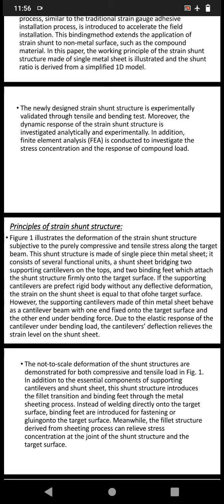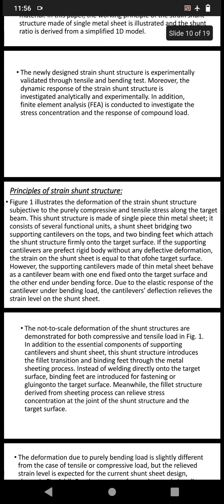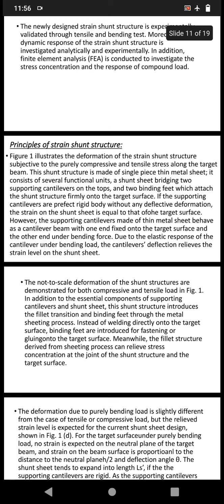If the supporting cantilevers are perfectly rigid bodies without any deflective deformation, the strain on the shunt sheet is equal to the target surface. However, the supporting cantilevers made of thin metal sheet behave as cantilever beams with one end fixed onto the target surface and the other end under bending force. Due to the elastic response of the cantilever under bending load, the cantilever's deflection relieves the strain level of the shunt sheet. The not-to-scale deformation of the shunt structures is demonstrated for both compressive and tensile load in figure 1.